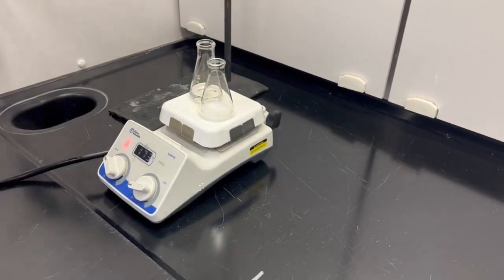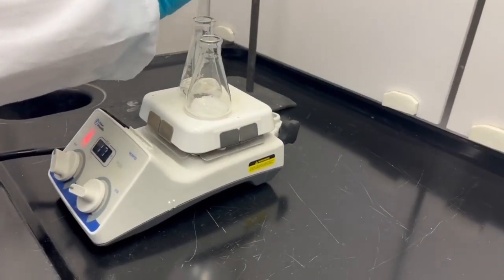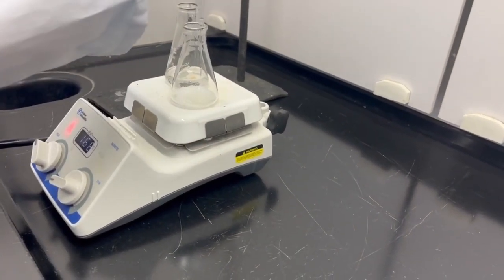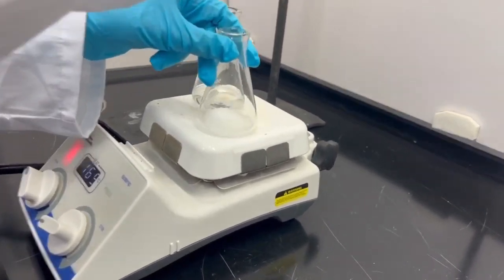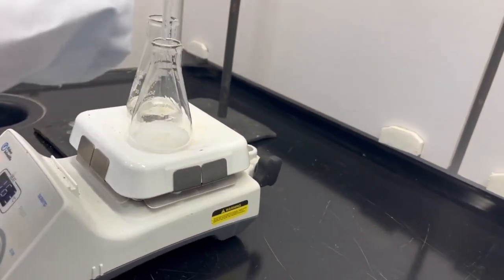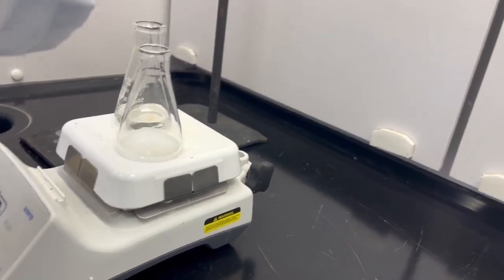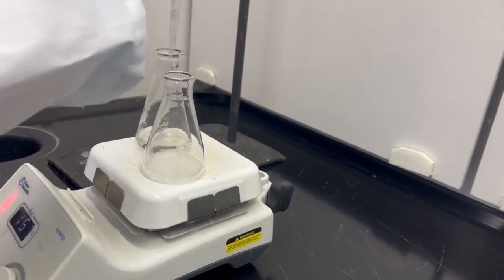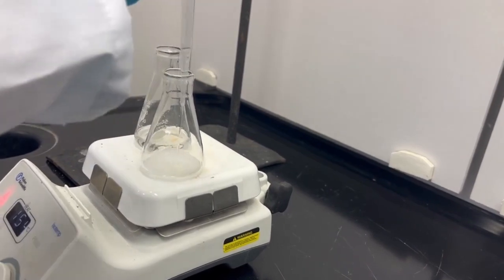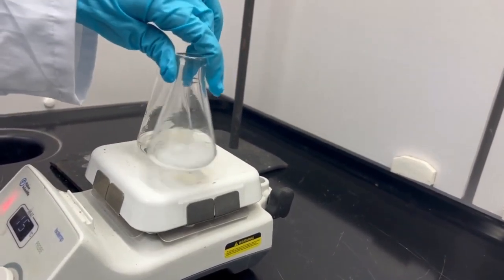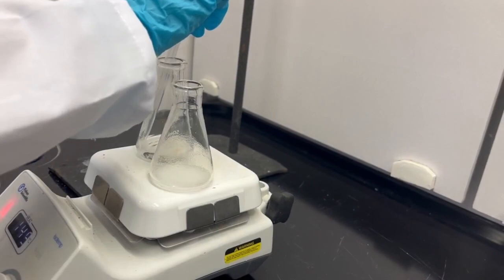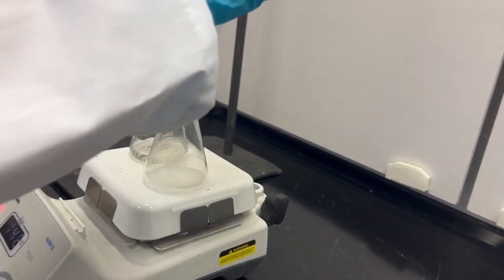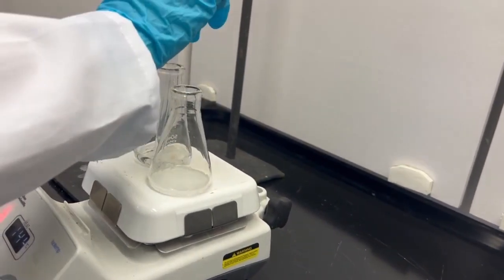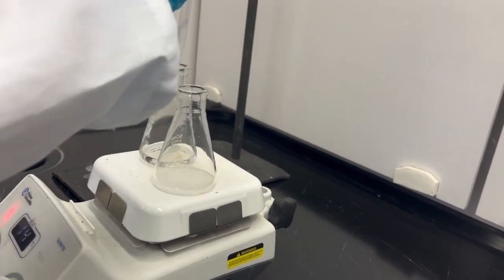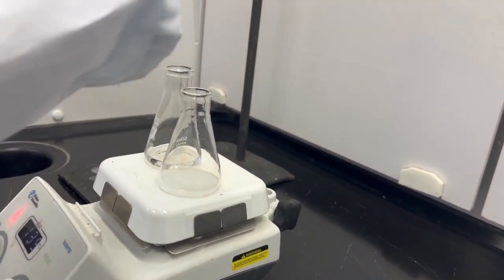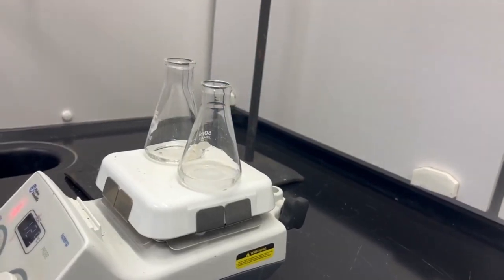With both flasks on the hot plate, carefully add some of the boiling solvent to the compound to dissolve it. If you are working with a known solvent, go ahead and add all of your hot solvent. If you had an unknown solvent, keep in mind that it's important that you only add the smallest amount needed, plus a little extra, to dissolve all of your compound. So add a little at a time until your compound dissolves fully, and then add a little more to ensure that your compound remains dissolved. Continue heating and occasionally swirl to help dissolve your solid.